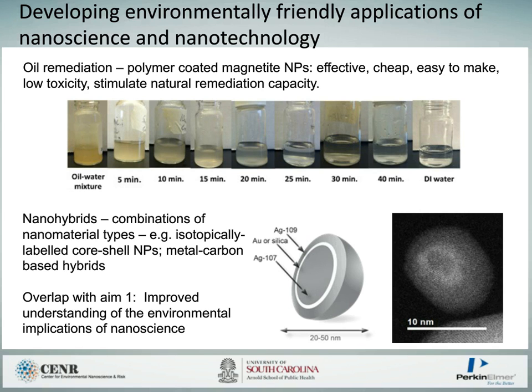And we're actually using the hybrids on the right, which are isotopically labeled core shell particles, to try and understand how nanoparticles are bioavailable, how they bioaccumulate in organisms, whether as a particle or do the particles dissolve and the ions are then taken up. And we do this by being able to separate the core material, which is one isotope, from the outer layer, in this case silver 109 in the diagram, which is partially soluble, and it's separated by an insoluble layer of gold or similar material. And using this combined with ICP-MS and single particle ICP-MS and other techniques, we can hope to answer that question of whether bioavailability is driven by direct particle uptake or is driven by dissolution followed by uptake of the ion, the silver ion in this case. So there are clear links between these two aims, particularly in that case where we're trying to use novel, environmentally friendly nanomaterials to answer questions that are important in nanotoxicology.